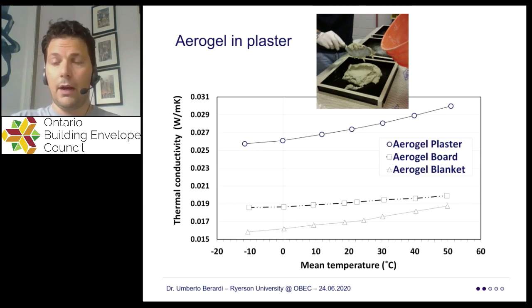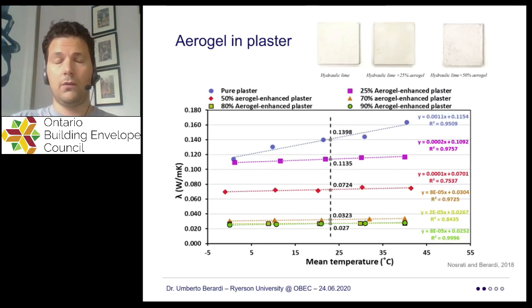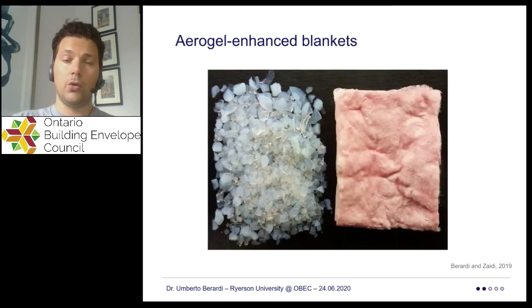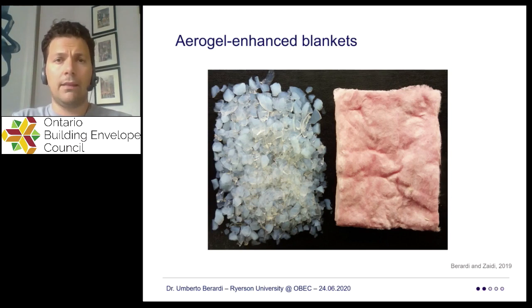They don't suffer a lot of aging, thanks to the fact that the aerogel is typically water repellent. They also behave well when it comes to the fact that they do not really get wet, so hydrothermally, they are good products. In fact, aerogel-enhanced blankets have started being more and more common, for example, for protecting thermal bridges in specific construction typologies. What is an aerogel-enhanced blanket?